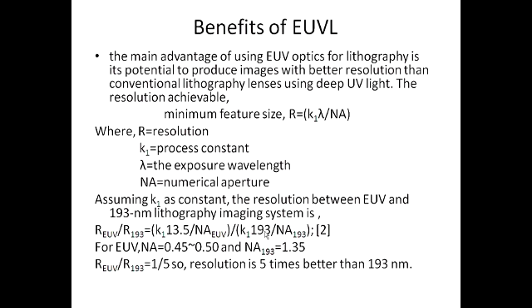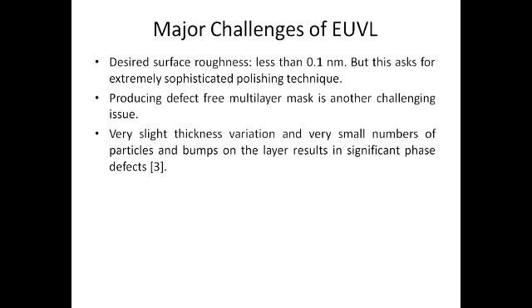The numerical aperture used for EUV is basically 0.45 to 0.5, and for 193 nanometer, 1.35 is chosen. From the equation, if we compare the ratio, you can see that in the case of EUV, this is 5 times better than the 193 nanometer case. So of course it's better, but there are a few obvious challenges in EUV lithography.